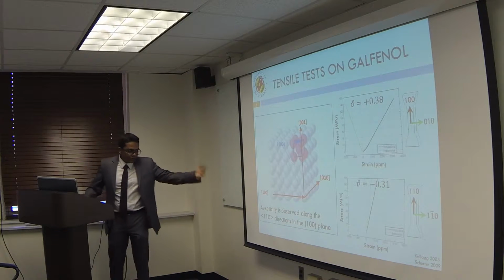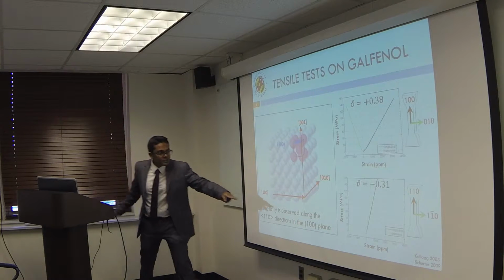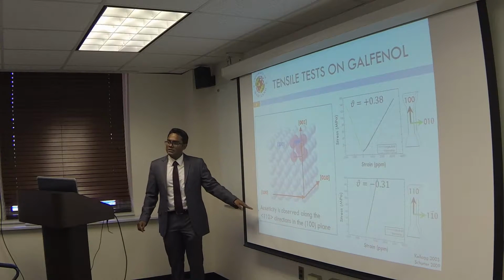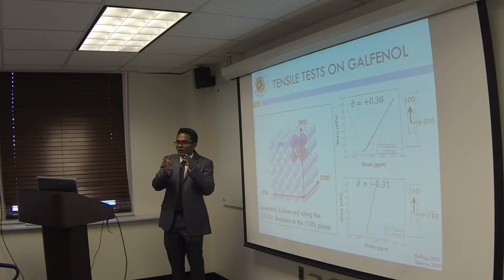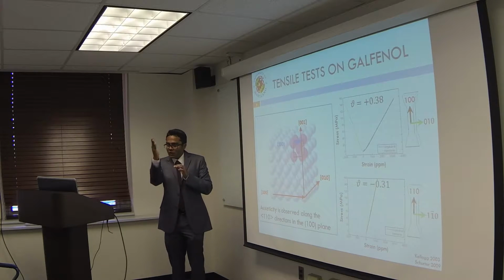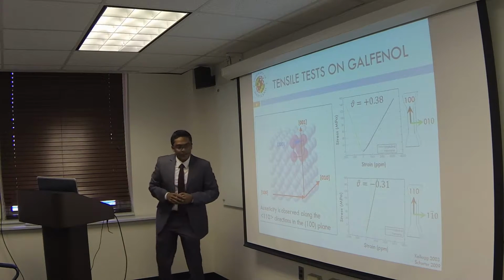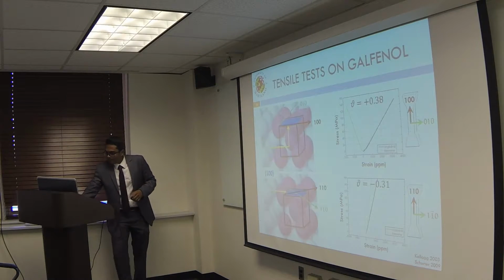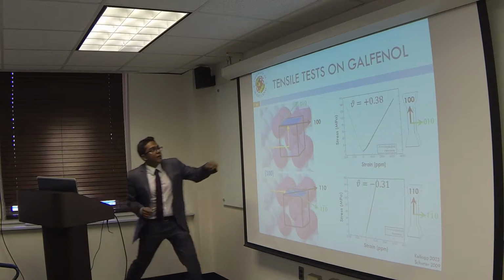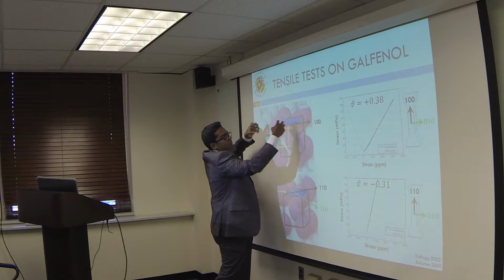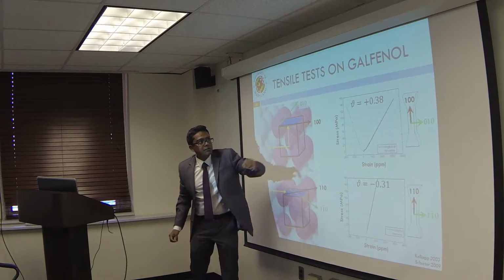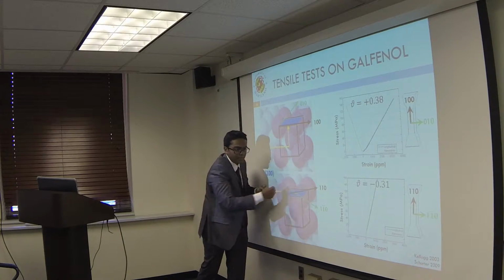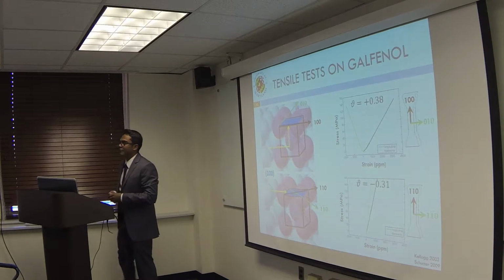So as you know, Galfenol exhibits auxeticity on the 100 plane along the 110 direction. So it's along one of the faces of the cube, and it's along the diagonal of that face. If I'm pulling those samples going this way, I would see a positive Poisson's ratio, whereas if I'm pulling the sample along the diagonal, I would be seeing a negative Poisson's ratio.